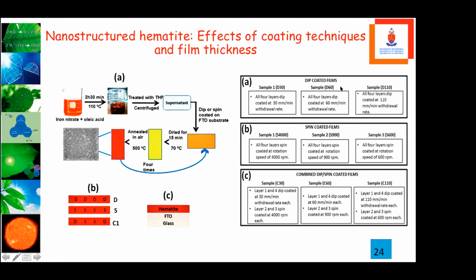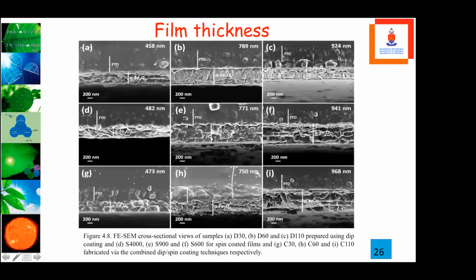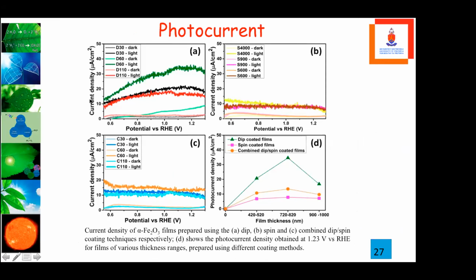So the work that we have done in our lab is varying the different methods, using either dip coating or spin coating or combining the two. And the results, let me just go to the photocurrent results. You can see that the dip coating is here in A, and then spin coating is in B, and the combined spin coating and dip coating methods were not giving us the best results. They were very bad. But if you take one of the two, you find that you are doing much better.